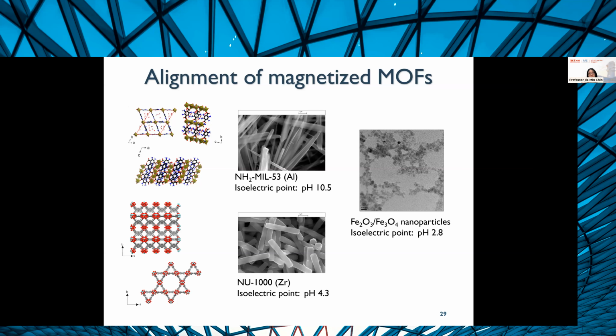And we want to do this in a very simple way that is very widely applicable to all sorts of metal-organic frameworks, not just one or two examples. But in this case, we took amino-MIL-53 because, to be honest, we had that. And also it's a needle-shaped MOF, so it allows us to very easily see that orientation almost immediately. And we took NU-1000, which is also, in this case, a rod-shaped MOF. And both of them are very anisotropic with one-dimensional channels. So they both have isoelectric points of 10.5 and 4.3 respectively.